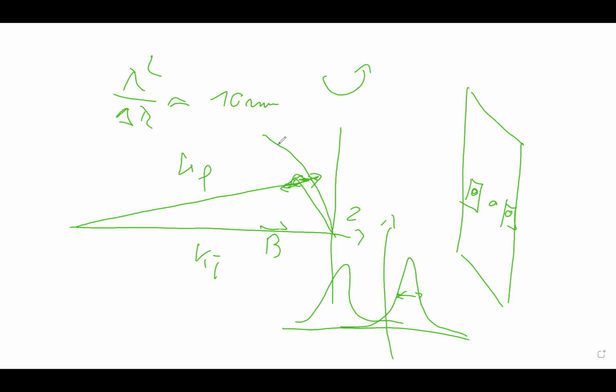I know about the importance of it, because it can tell us if the measurement is actually limited by the instrumental resolution, or if it's the real signal that we are observing. Exactly. Yeah, this is right, but it doesn't tell you why you measure a correlation length that is much larger than the coherence of your instrument. That should not be possible.